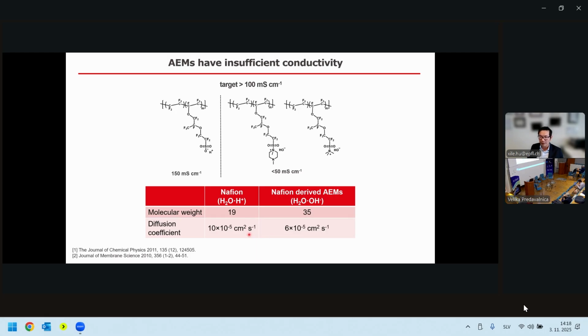Not to mention the proton can sometimes go through tunneling. And so in this case, we know that Nafion, for instance, at 80 degrees can conduct with a conductivity number of 150 millisiemens. While if you take the same Nafion backbone and you just transform it into an anion conducting moiety, it immediately decreased to less than 50. And so that's not sufficient, and people typically think it will be more than 100 millisiemens. That is enough, okay? And so that's the conductivity issue.